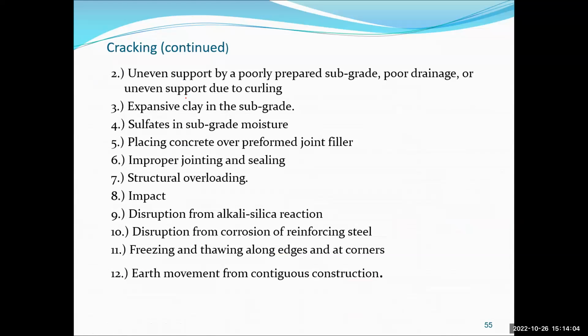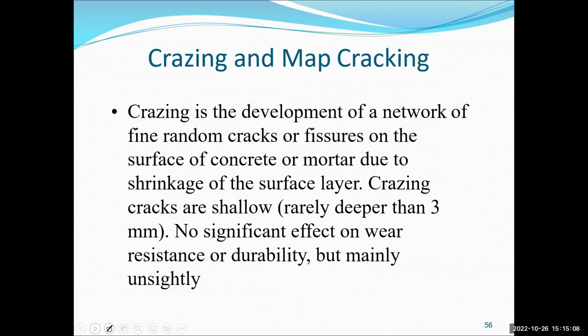Other kinds of cracks generated in the concrete could be due to uneven support by poorly prepared subgrade, and this is very common in structures. If you have a foundation that looks like this between two columns, I'm trying to draw it here. Obviously, they have doors and windows. See that? So what happened is that support settlement somewhere here. If this is settled, then it's going to create a crack in that direction around the corner, right? Expansive clay is also a force that can uplift and bring down the structure. We have sulfate resistance, improper jointing, and impact, and all of these can cause some cracking.